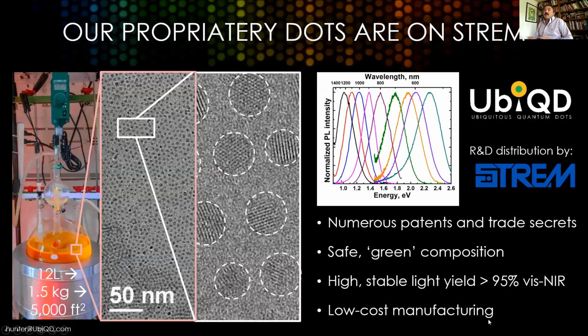So our materials are based off of copper indium sulfide, and sometimes we do copper indium selenide if we want to tune that emission. Very similar otherwise. We do a core shell structure. We have numerous patents and trade secrets related to this compound. We can get high quantum yield near unity, consistently above 95% through the visible and the near infrared.